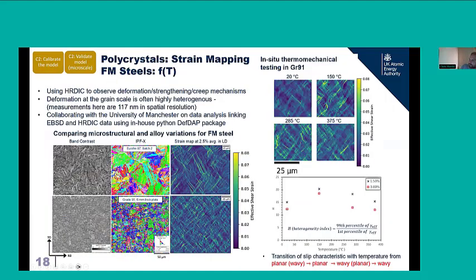Not only can we do this as a function of strain, but also as a function of temperature and of microstructure. I won't dwell on this slide for the interest of time, but just to show that we can do this on different variants of steel. So in this case, a coarser microstructure steel versus a finer microstructure. And as a function of temperature up to 375 in this case, looking at the effect that temperature has on the deformation mechanisms and ensuring that we can represent that in modeling.